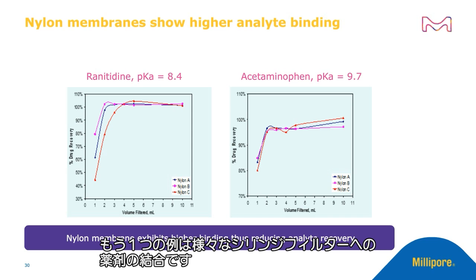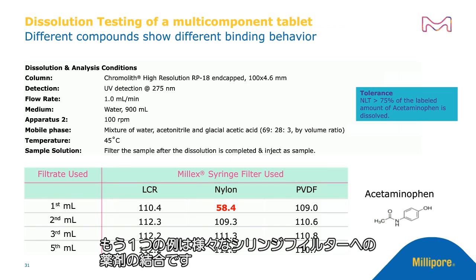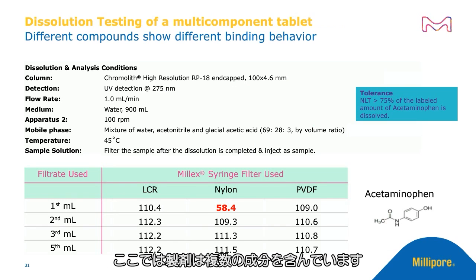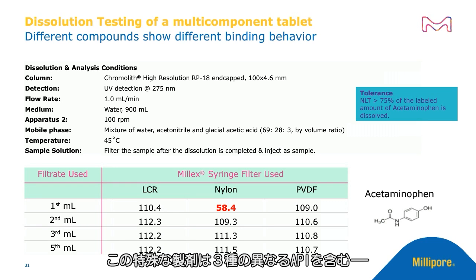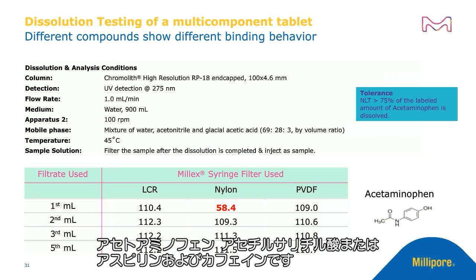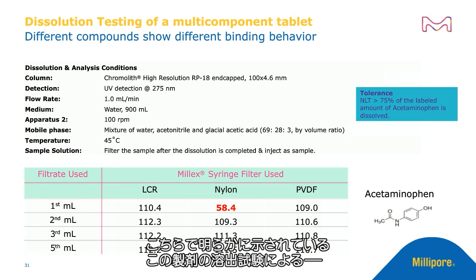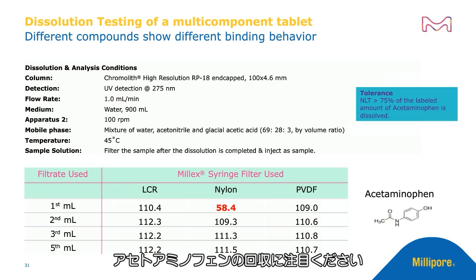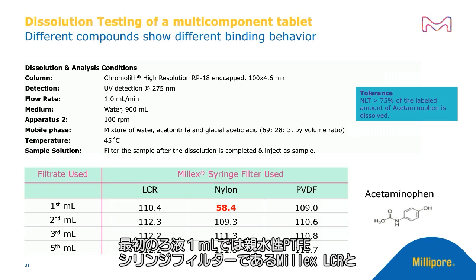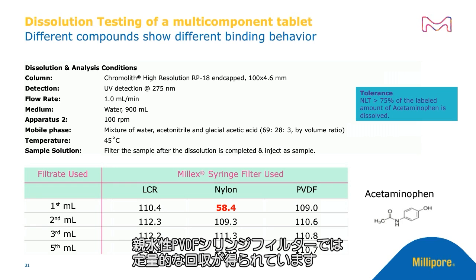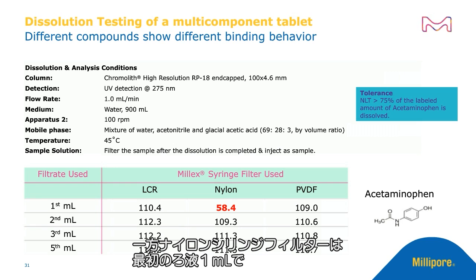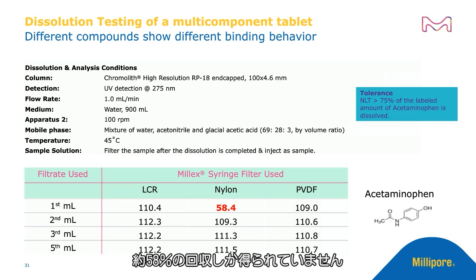Here is another example of drug binding to various syringe filters where the formulation contains multiple components. This particular formulation contained 3 different APIs of interest: acetaminophen, acetyl salicylic acid or aspirin, and caffeine. As you can clearly see on this slide, when it comes to acetaminophen recovery following dissolution testing of this formulation, for first ml of filtrate, the hydrophilic PTFE syringe filter, that is Millex LCR, and hydrophilic PVDF syringe filter show quantitative recovery. Whereas with the nylon syringe filter, for the first ml of filtrate, you only get about 58% of recovery.